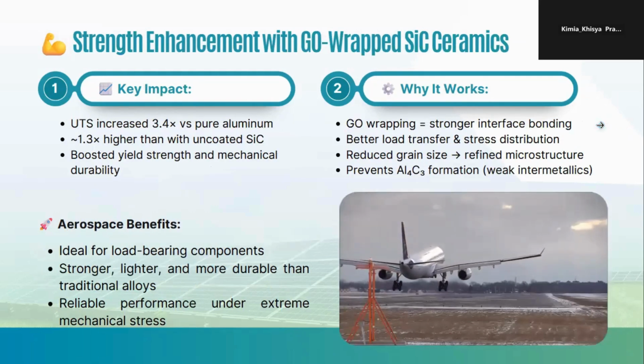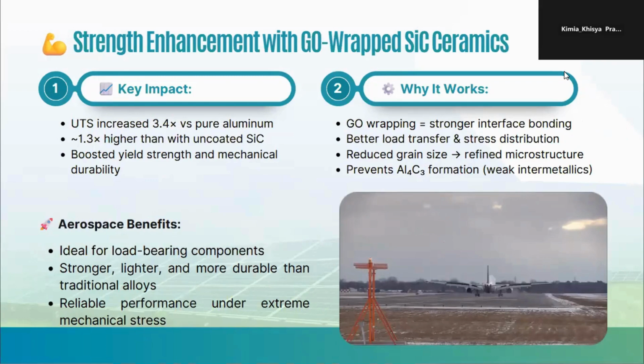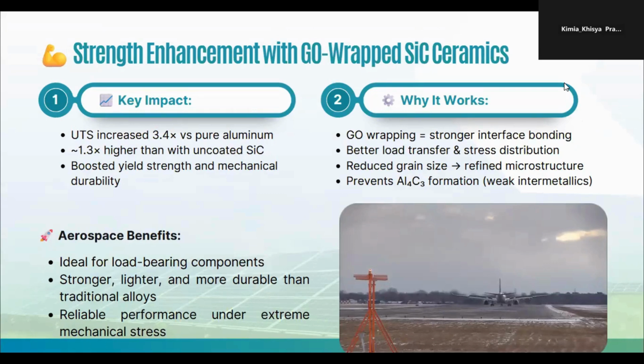The last one is strength enhancement with graphene oxide wrapped silicon carbide ceramics, because UTS increased 3.4 more than pure aluminum and 1.3 higher than uncoated silicon carbide, boosting yield strength and mechanical durability. This works because graphene oxide is stronger in interfacial bonding, giving better load transfer and stress distribution, and reducing grain size. It means it refines the microstructure and prevents aluminum carbide formation because it is a weak intermetallic.